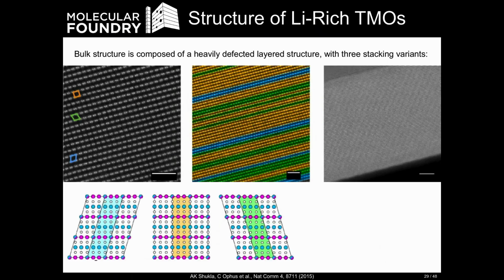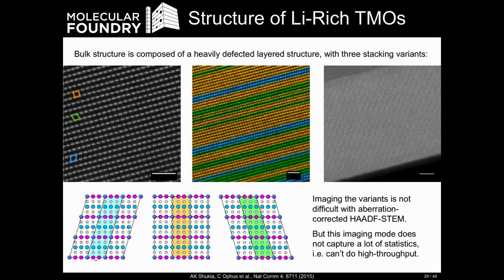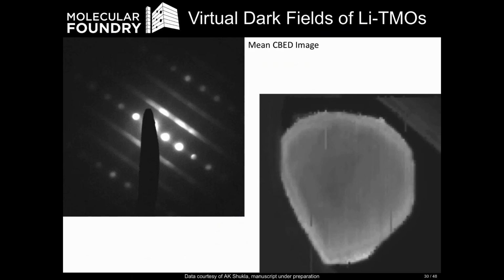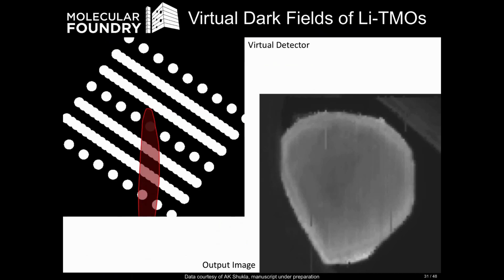These three different stacking sequences form very slightly different diffraction patterns that we can use to measure which of the three variants is directly underneath the probe. What this looks like is a data set like this. On the upper left, I've shown the mean CBED image for these lithium-rich TMOs, and on the right, a virtual dark field image. If I put a mask over the sample and fit where these diffraction spots are, I'm just showing where the beam stop is here on the center probe. I can make a virtual dark field just like we did in the previous data set and form an image. And that's what I'm showing on the right here.